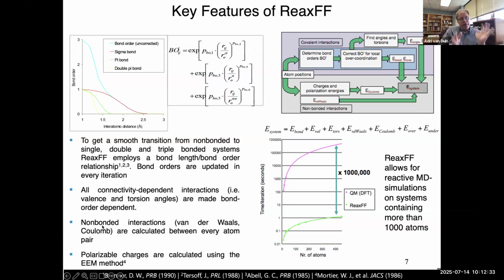So ReaxFF, because it calculates an on-bond Coulomb interaction, can make a transition between a covalent material where there's not much charge on a bond and an ionic material where there's actually a lot of polarization on a bond. So for a highly polarized bond, the Coulomb interaction provides most of the bond strength, while for a covalent bond, like a bond between nitrogens in N2, for example, that is almost exclusively bond order based. So you can actually switch between ionic materials and covalent materials.